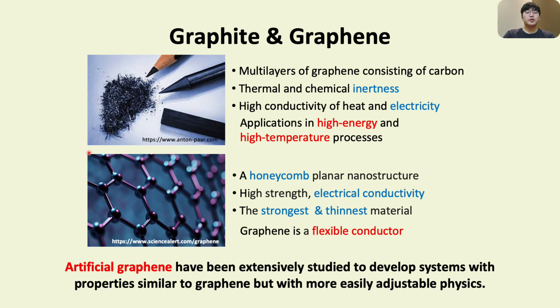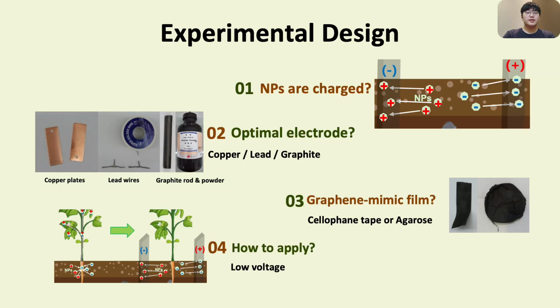Graphite consists of multiple layers of carbon and has high heat and electrical conductivity. Graphene is a single layer of carbon atoms and is also a flexible conductor. But it is challenging to mass produce pure graphene, so I focused on artificial graphene and developed a film that mimics graphene. In this study, I confirmed whether nanoplastics have electromobility, which electrode is optimal for the electrical capturing of nanoplastics, how graphene can be mimicked, and whether the graphene mimicking film can be used for inhibiting the penetration of nanoplastics into crops.